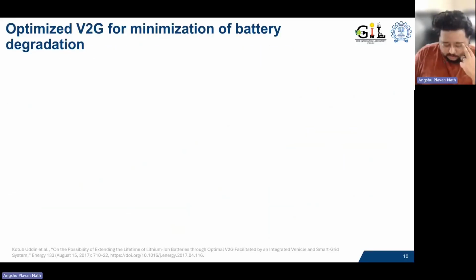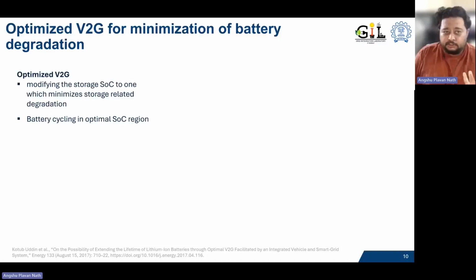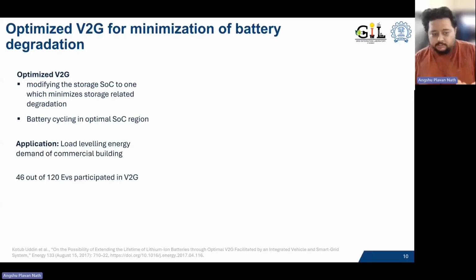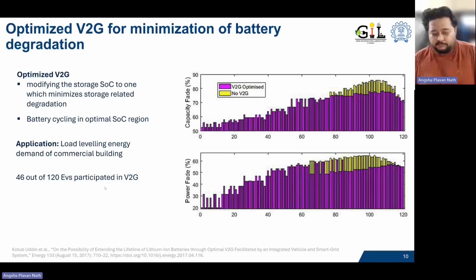Then there is one more case study where they went for optimizing V2G for battery degradation. They wanted to minimize the battery degradation because of V2G. So they modified the storage SOCs and they modified the battery cycling in the optimal SOC region. And they did this load leveling application, and 46 out of 120 EVs participating in this project. So what they actually observed was, without any V2G, the degradation is much faster compared to an optimized V2G algorithm. Because of the optimized V2G, they're able to slow down the degradation, and the effect on the batteries was much better compared to if there had been no V2G.